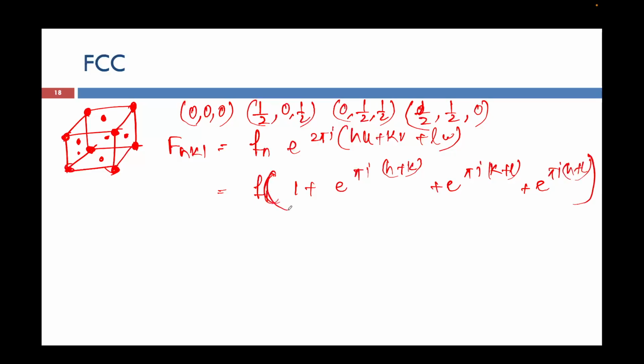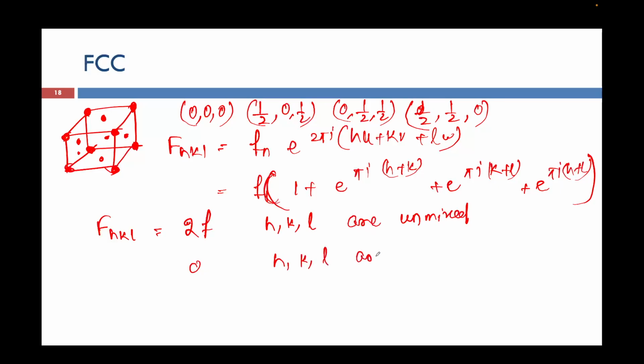So the condition for hkl will be: you will be getting 4f when hkl are unmixed, and 0 when hkl are mixed.